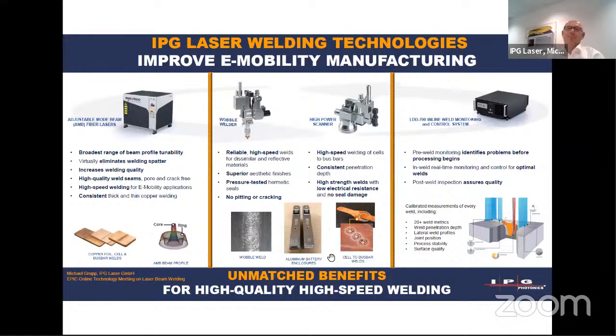So this was the one technology, the single mode lasers, and the other technology I already mentioned is our new technology of the adjustable mode beam. So we get a very broad range of beam profiles. This means we can separately adjust the power in the ring. We can separately adjust the power in the core and play with these parameters to optimize our process. In this way, we can create also wider weld beads, narrow weld beads. We can increase the quality of the weld seams. We can create really high-speed welding, and we can really get consistent welding in thick and thin copper.